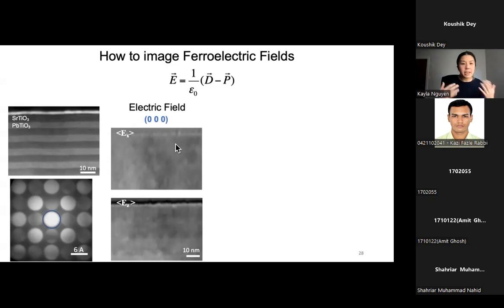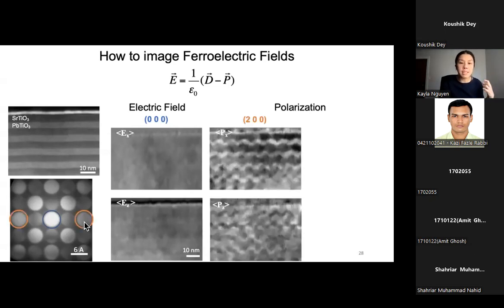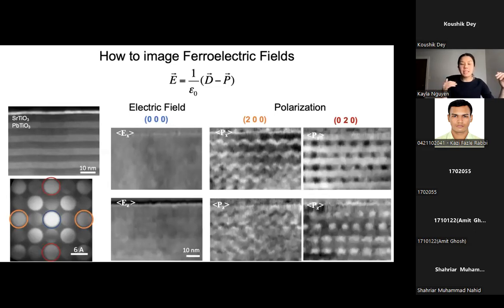And so what we find is that our electric field is pretty flat. We're not getting a lot of structure in it. So that means that there's not much going on with the electric field. Now, if we take, for example, the 200 disk, which is the distance of titanium relative to lead, we can get back information related to polarization. That is because polarization requires conjugate pairs, and conjugate pairs break symmetry. And if you look at the 020 disk, that also breaks symmetry. And so now you have information related to polarization in the X and in the Y direction.